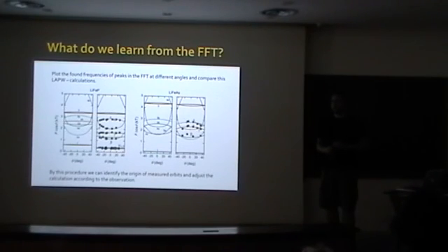I think it's a problem due to the surface. If you do a band structure calculation and you change your pnictogen height slightly, that can give you different results, right? And if you look at other papers on barium 122, it is suggested that the surface would have a different pnictogen height than the bulk has. That might explain why the band structure that they see corresponds to their ARPES data, but this would not be the bulk, this would only be the surface.